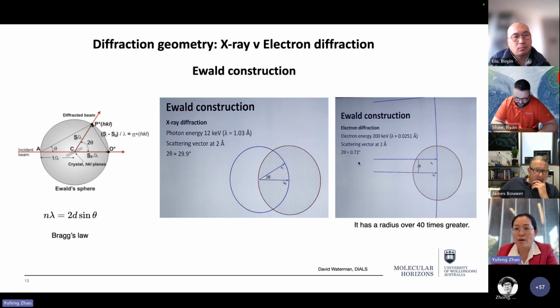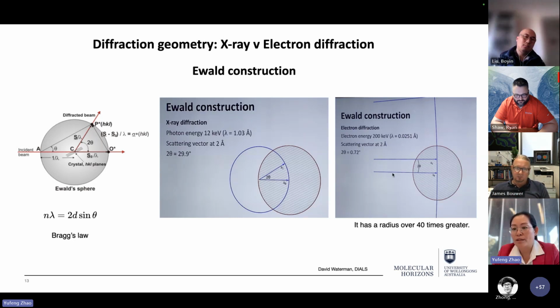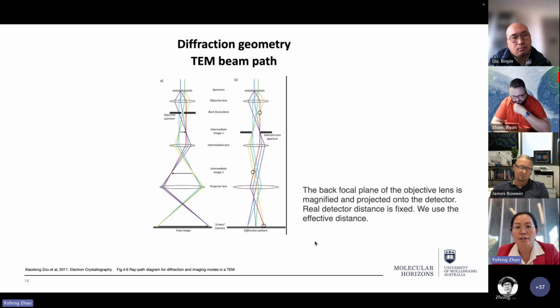But we have much higher voltage, 200 keV, and the wavelength is about 0.0251 angstrom. With the same scattering vector at 2 angstrom, this 2 theta angle is only about 0.72 degrees. This angle is so small that if we want to build an Ewald sphere, the radius would be really, really long. You can imagine a tiny angle and a really long radius giving a huge ball. So in a real experiment, the Ewald sphere is more like flat, with nearly no angle. This means the geometry is quite challenging.